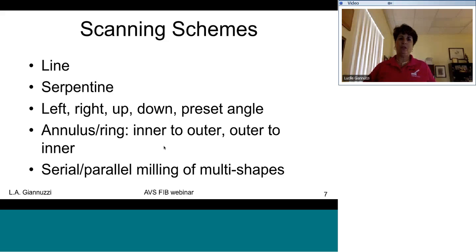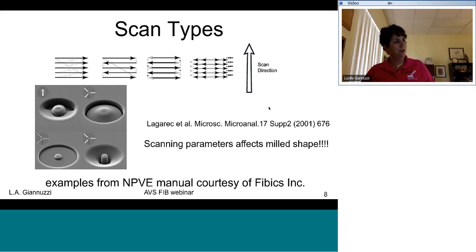Scanning speed. You can scan in a line, in a serpentine, from left to right, right to left, up to down, down to up, at a preset angle, inner to outer or outer to inner. And we'll also talk about serial or parallel milling and when that's important to use. So here are different scan types, and this shows this extremely well with a single type of pattern. Here we're using a pattern defined by an outer diameter and an inner diameter. Depending upon how we scan the beam will very much depend on what our ultimate shape results in, because this depends on where the sputtered material will redeposit, okay?